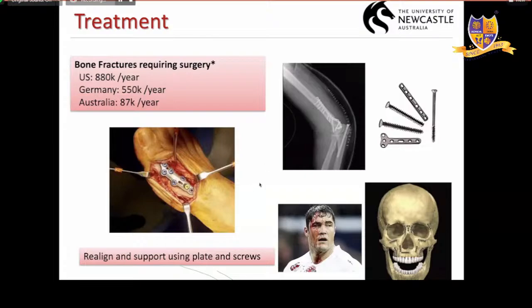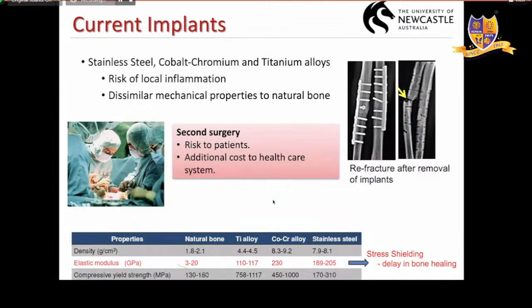So what are these materials made of? Currently, the materials for those mini implants are stainless steel, cobalt, chromium, and titanium-based alloys. If you leave these materials for a longer period of time, there is a risk of local inflammation. It can undergo wearing. Wearing means rubbing of the metal against the bone, and can cause debris of metal particles, which can be very inflammatory. Leaching of ions can also lead to failure of the implant and cause inflammation.